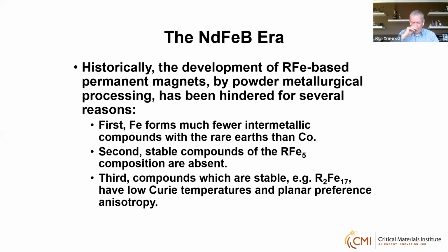Now, what happened next was there was a search for a combination of a light rare earth element with iron. Unfortunately, unlike rare earth cobalt, the rare earth iron system tends to form much fewer intermetallics. And those that do form tend to have low Curie temperatures and also display planar anisotropy. So it was realized that the binary systems were probably not going to provide a suitable candidate material. So the search was open to multi-component systems and metastable phases.